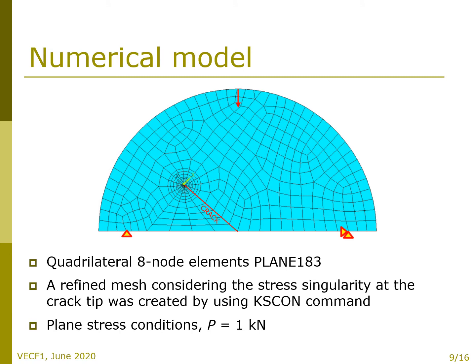The following figure represents the numerical model of the semicircular disk with an inclined crack under 3-point bending. The model was created in ANSYS finite elements system. The task was solved as two-dimensional and the specimen was modeled via quadrilateral 8-node elements denoted as PLANE183. A refined mesh considering the stress singularity at the crack tip was created by using KSCON command, and plane stress conditions were prescribed in order to be able to compare the numerical results with data observed experimentally on the specimen's surface.